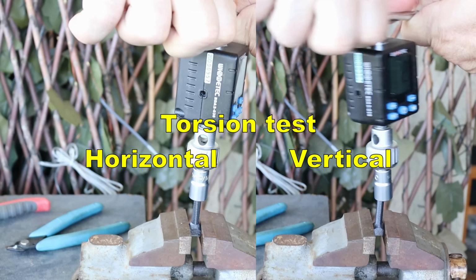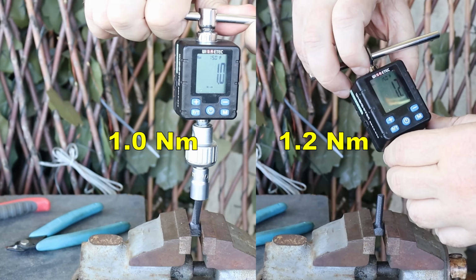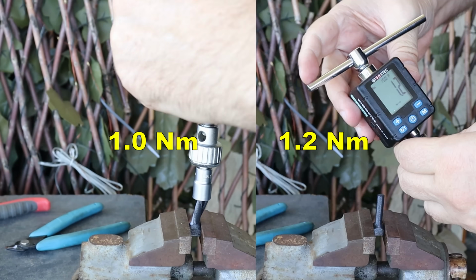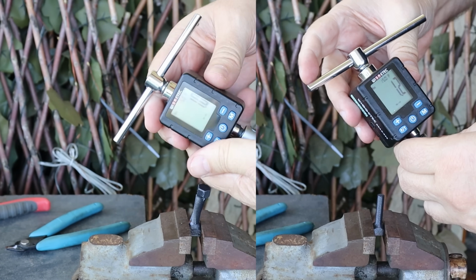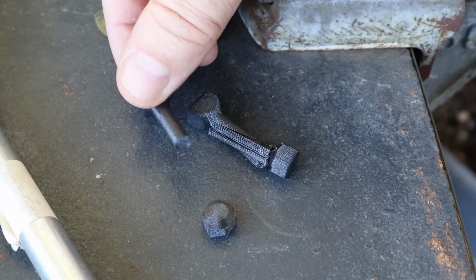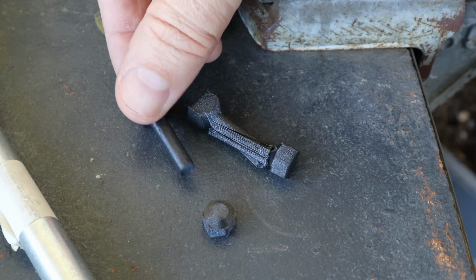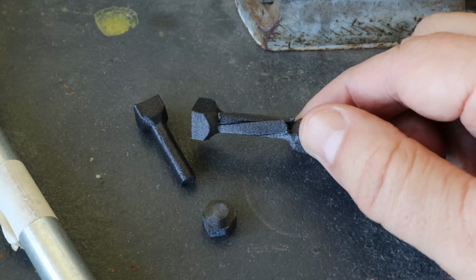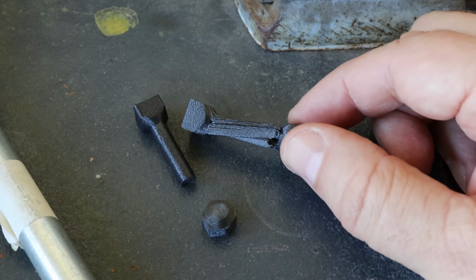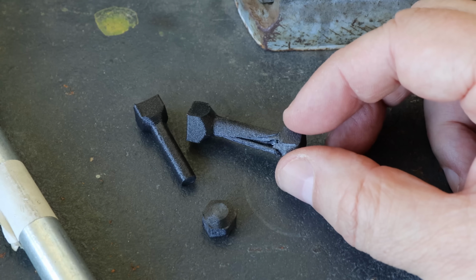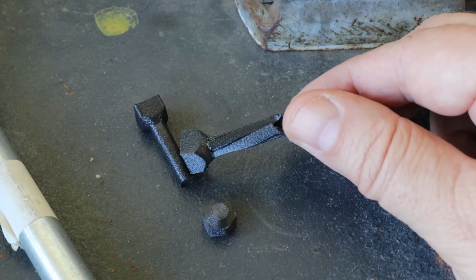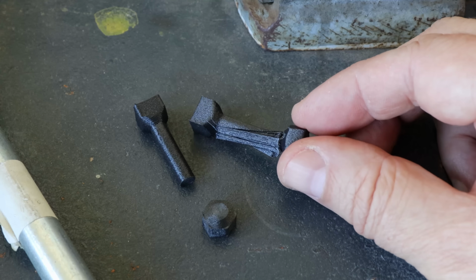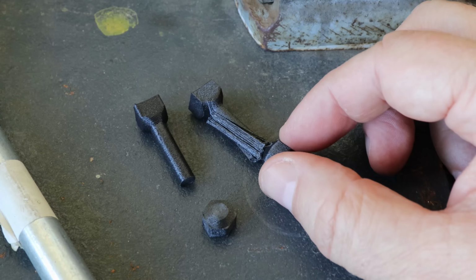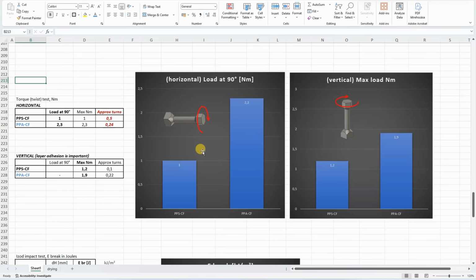Torsion test side by side, horizontal and vertical objects. This one printed in vertical position breaks very suddenly, no surprises here. But this printed in horizontal position breaks at quite a low load, and this is because of the weaker layer and wall adhesion. I'm not sure if you can see this on the screen too. Definitely with better layer adhesion, this would break at a much higher load. Unfortunately in this test, even if printed in horizontal position, it was quite weak because of that layer and wall adhesion.